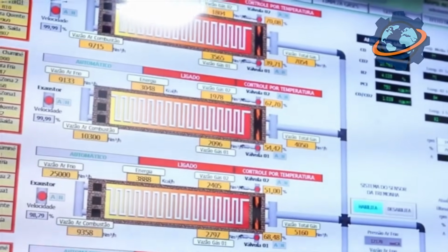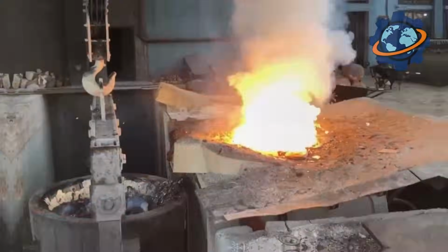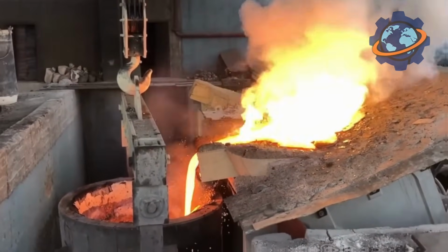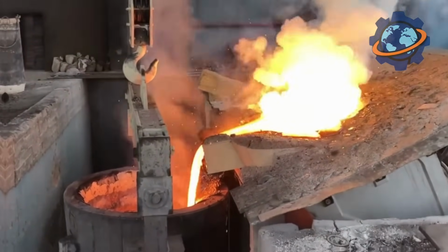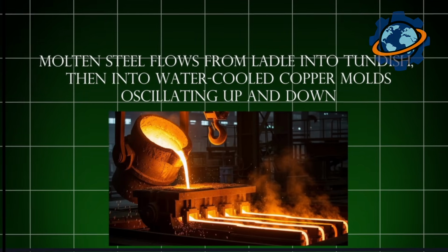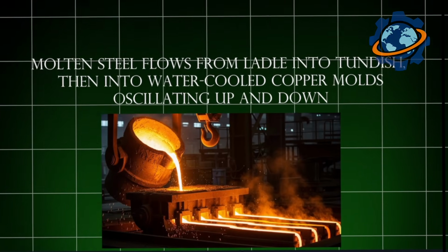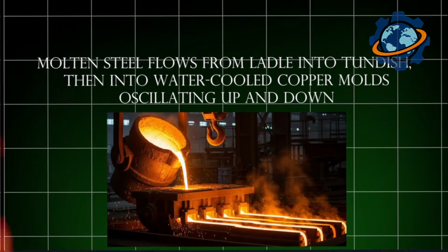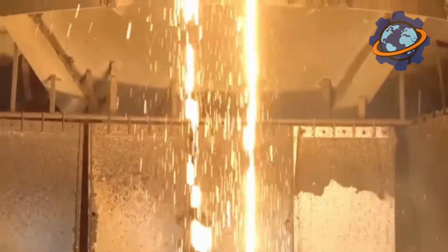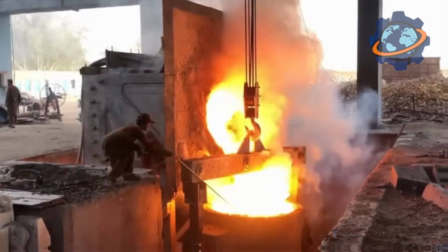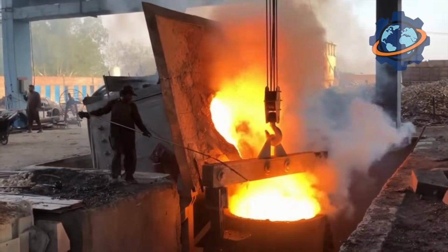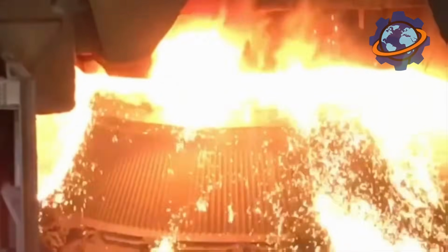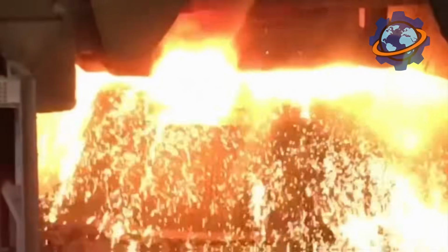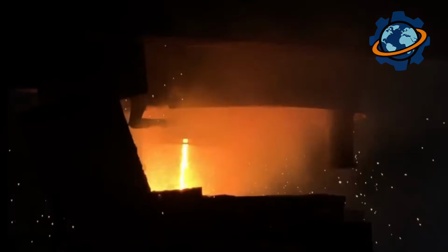The ladle, mounted on railcar, travels to continuous caster. This machine revolutionized steelmaking, replacing individual mold casting with endless process. Molten steel flows from ladle into tundish, then into water-cooled copper molds oscillating up and down. As steel contacts mold, outer shell solidifies while interior remains molten. The strand, continuous ribbon of steel 8 inches square, emerges from bottom at controlled speed, bent gradually from vertical to horizontal through roller system.